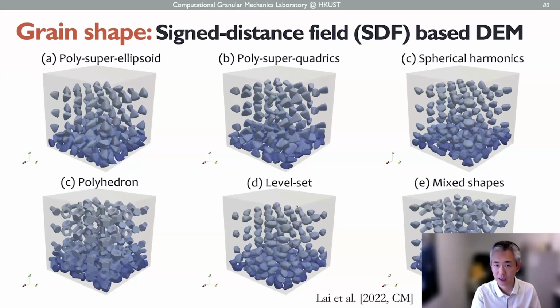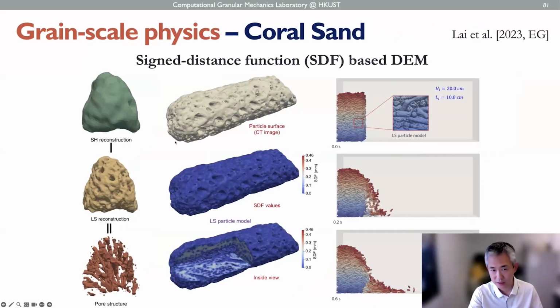And further, we have developed another approach, still using SDF, to generate this more complex granular particle. This is a coral particle here, okay? And this coral sand is featured by this double porosity, in a way that each individual coral sand has an internal pore. And then when you put such an assembly of the coral sand together, they have this interparticle pore as well. So we have this another kind of dual porosity structure.